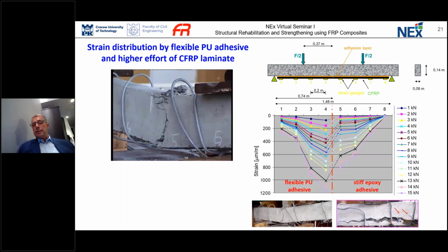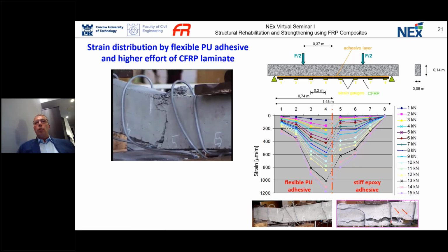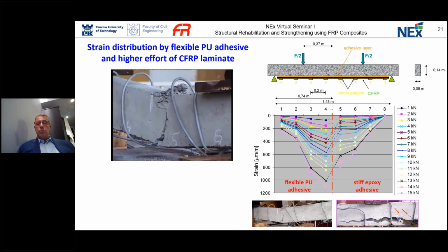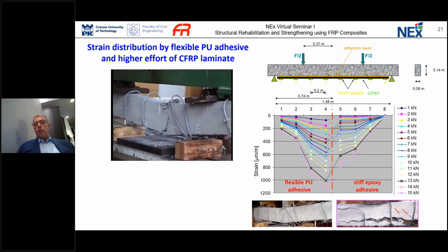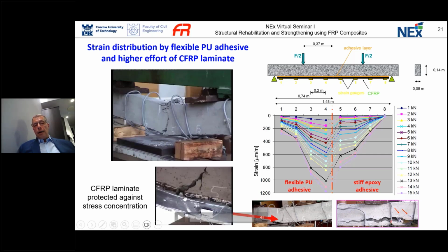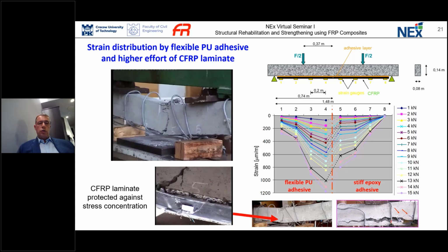If we compare the same system but with flexible adhesive, in this case, you can clearly see that the effort is higher. Also, as you can see in this movie, the system is hanging on the composite material, even if the structure is very seriously damaged, and it is able to transfer load and also to warn people and allow people to escape. Even after removing this part, you can clearly see that this kind of flexible material is able to dissipate energy and clearly show how it protects the composite material against stress concentration. So the composite material is not damaged.